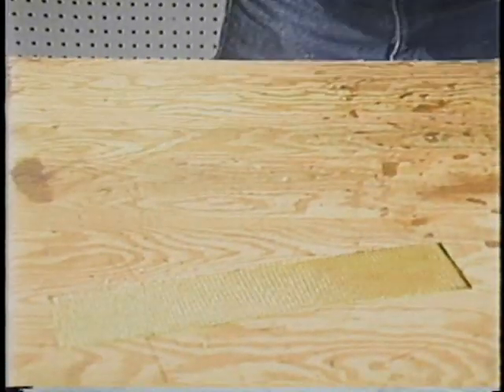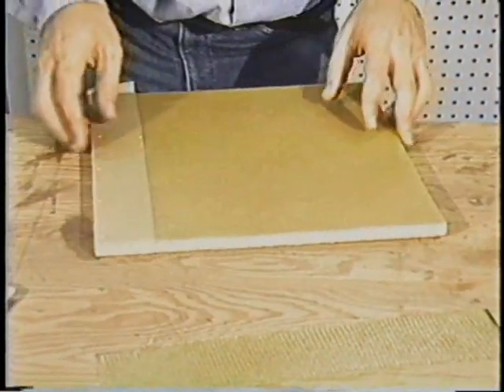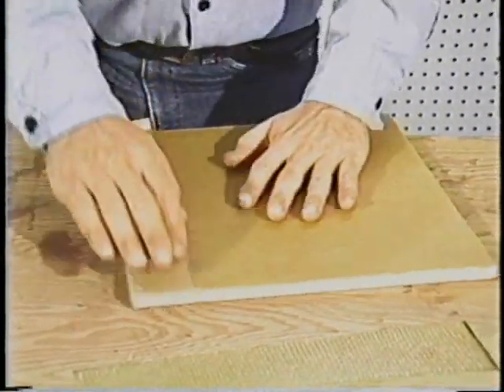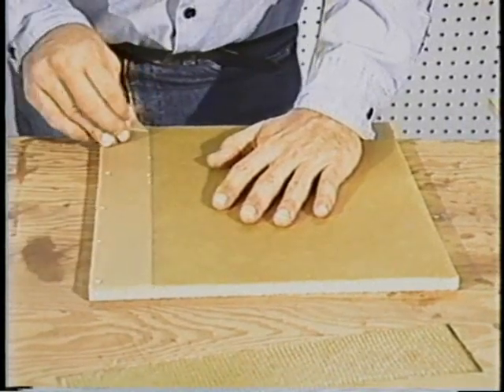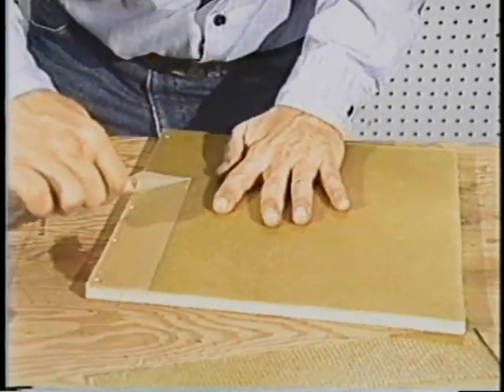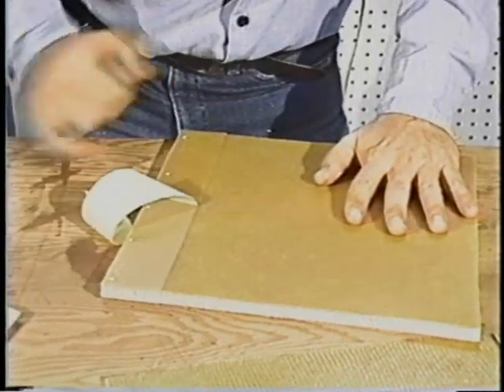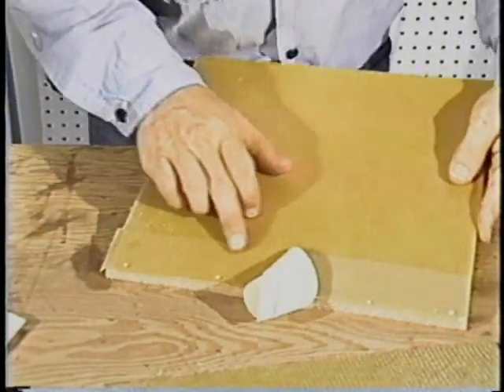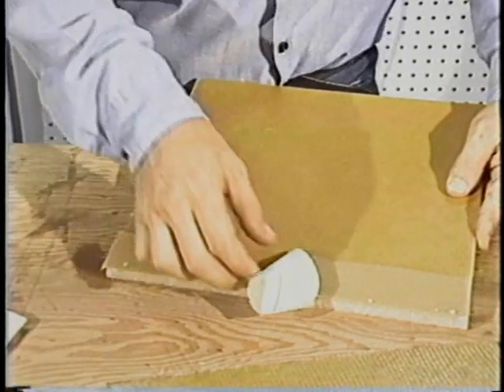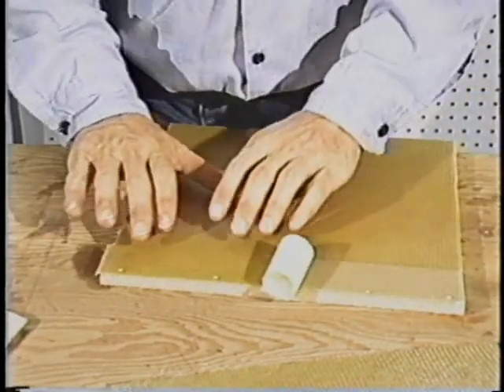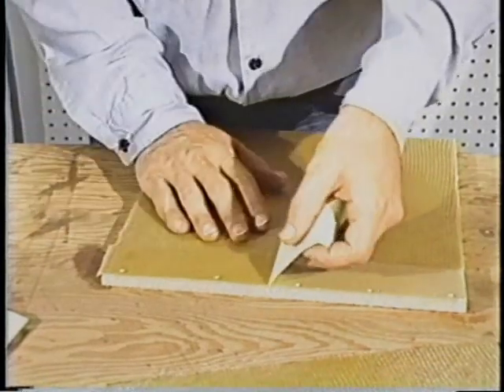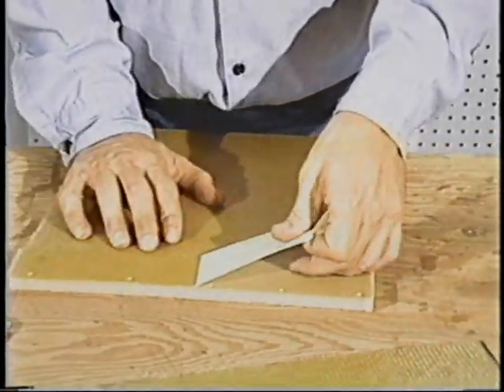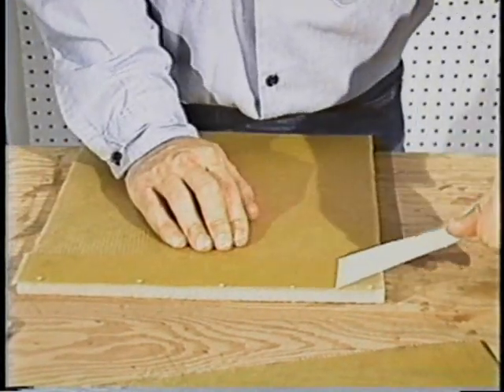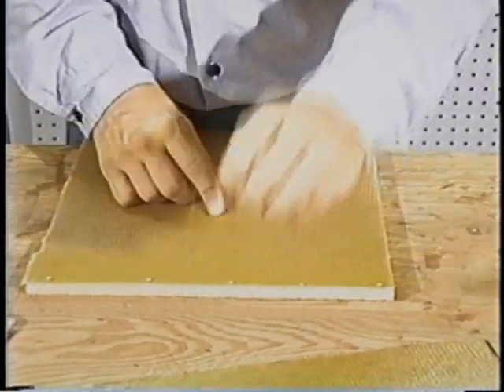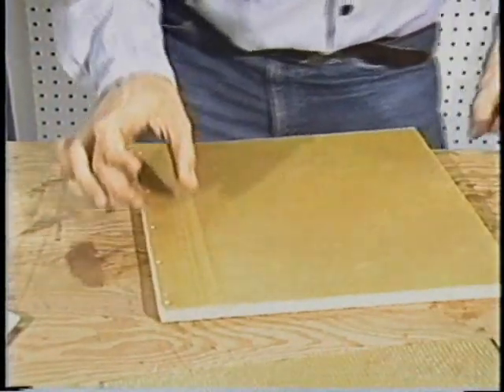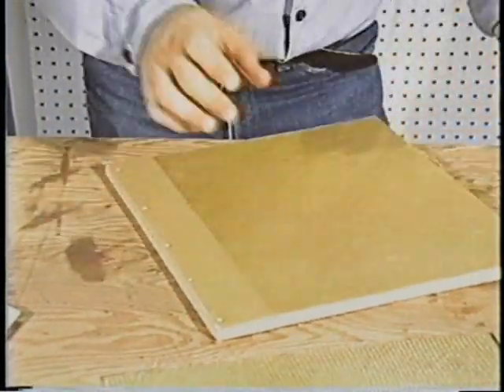There's our tape. Now we have our part that we already laid up, our sample piece. We have our peel ply. Now we're going to remove the peel ply. It's cured already, completely cured. Notice as we pull off the peel ply, the surface behind the peel ply has a matte finish. This is the weave of the cloth showing up. We have peeled off this protective covering and we now have raw, clean epoxy that's never seen the light of day before. It's very easy to pull off and it's very clean. This will make a perfect surface to join to the other part.